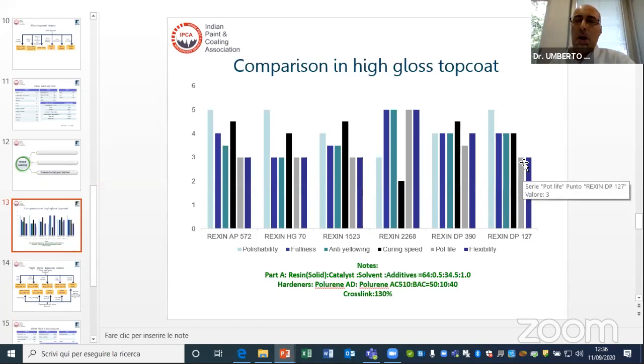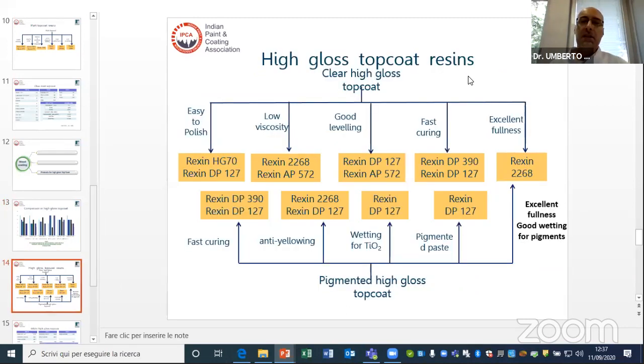In this case, our selected product is Rexin DP127 that we can see as a very good balance between all the properties, speaking about polishability of the system, fullness, anti-yellowing, curing speed, pot life, and flexibility. In this table, we can see that the product is suitable for high gloss top coat resins, for clear high gloss effect, and also for pigmented high gloss effect. The system is easy to polish.